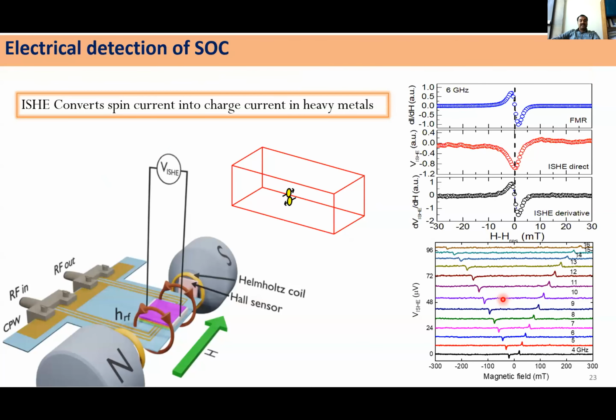And as I mentioned, we can also electrically detect the spin current through this heavy metal. So we inject the spin current, and by using the inverse spin Hall effect, the spin current will be converted into a transverse charge current. By using copper electrodes, we have measured the inverse spin Hall voltage. So as you can clearly see, whenever there is ferromagnetic resonance happening, there is a voltage across our sample that tells us that the spin current that is injected into the non-magnetic material is converted into a voltage